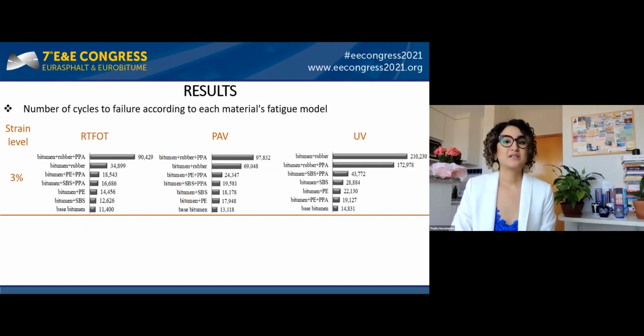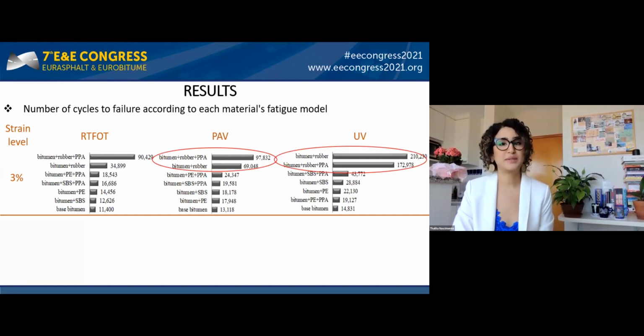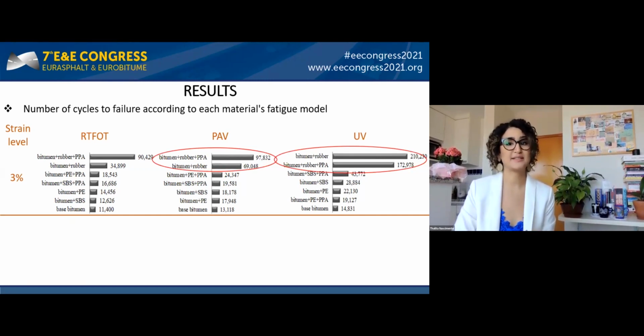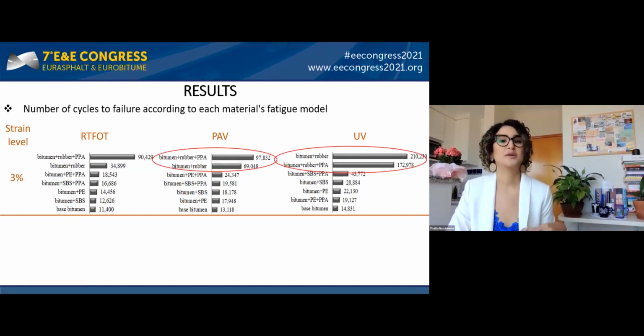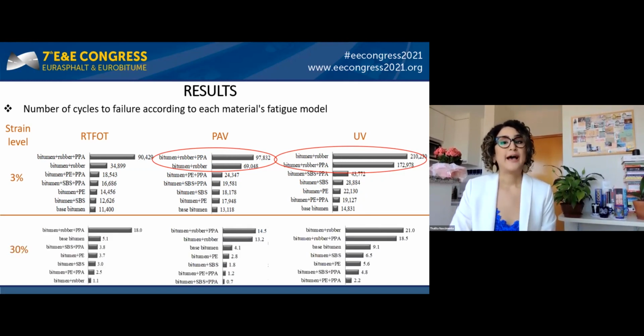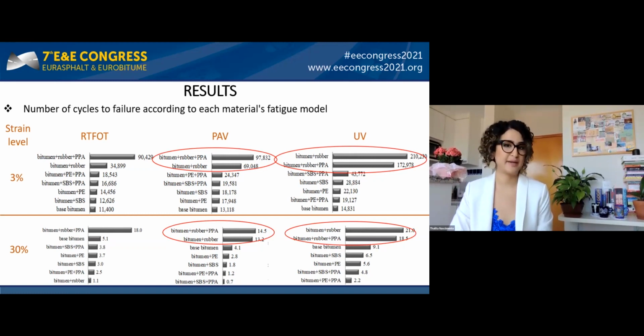The analysis based on the viscoelastic continuum damage, VECD, shows that for a low strain level of 3%, which represents pavement with low deflections, the bitumen plus rubber and rubber plus PPA presented the longest fatigue lives for both long-term aging levels. For a high strain level of 30%, the bitumen plus rubber and rubber plus PPA also present the best performances for both long-term aging levels.